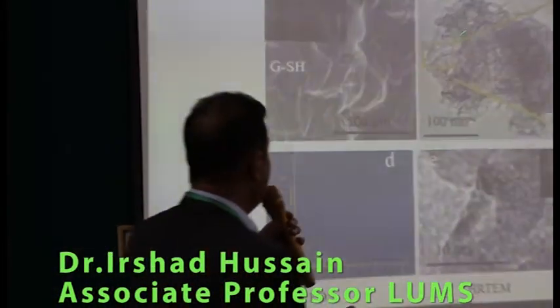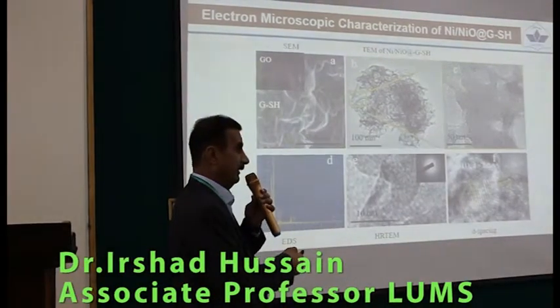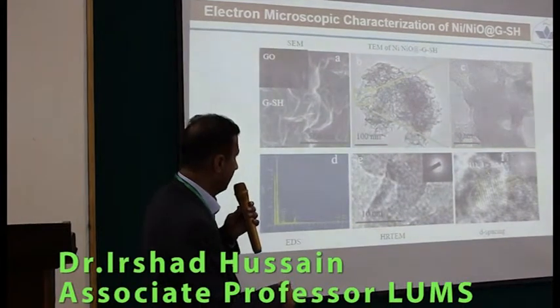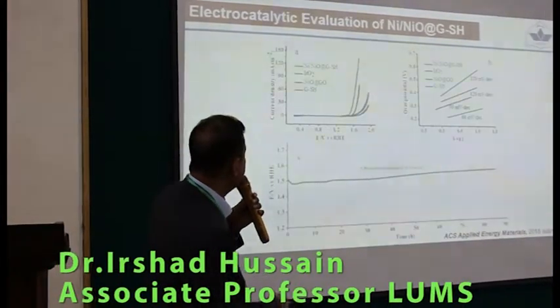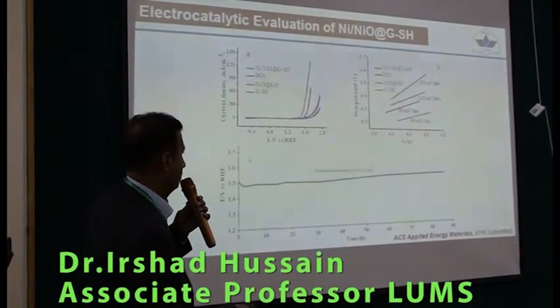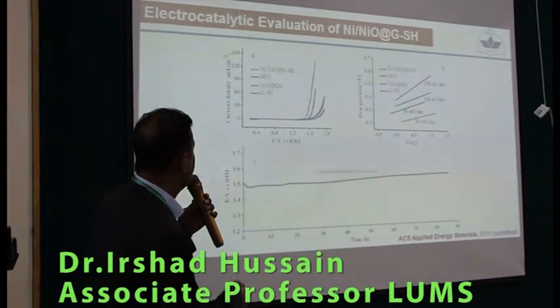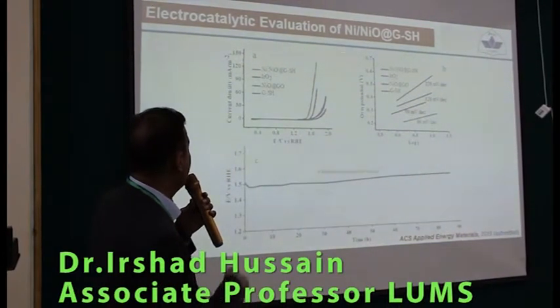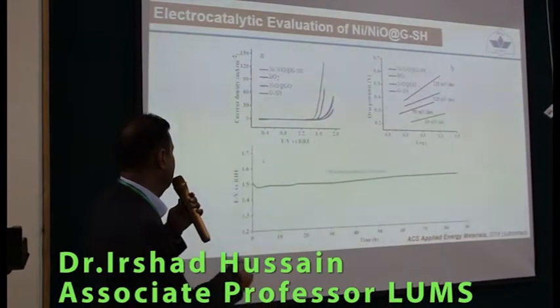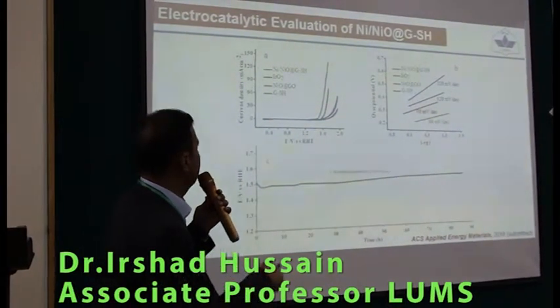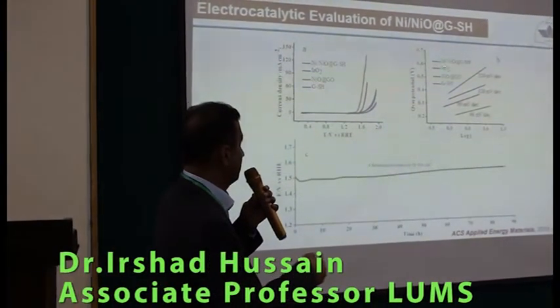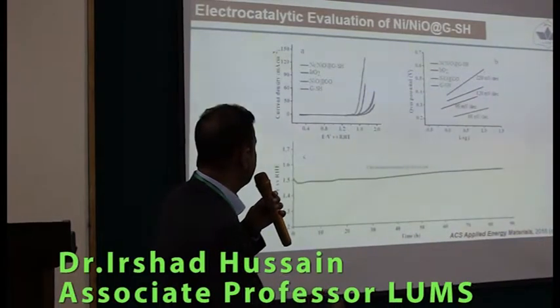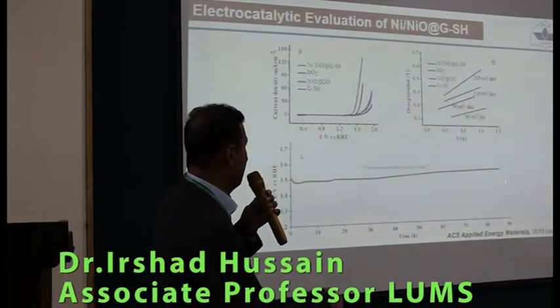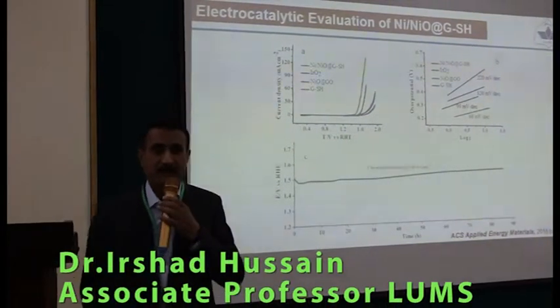More recently, what we have done, we have generated nickel particles on graphene sheets. And then we found that they are less than 1 nanometer. And they are extremely effective. So this one, we just got a very good review from ACS Applied Energy Materials. And if you look at these kinds of graphs, all these parameters, I don't want to go into technical details, they show they are highly effective, even more effective than the best catalyst nowadays, that is iridium oxide, and they are extremely stable. Even after 90 hours, they are maintaining more than 90% of their electrocatalytic activity. That is really amazing in this case.